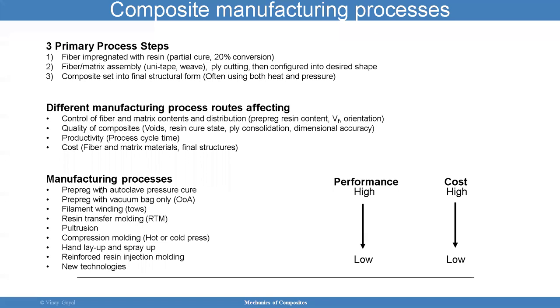So we have the pre-preg with autoclave pressure cure. So you're going to have that pre-preg, which is partially cured. The fiber and the resin are partially cured, meaning that it's semi-hardened. You can still mold it, and the resin can flow once it's heated up. So you can put it into an autoclave with pressure to cure it further.